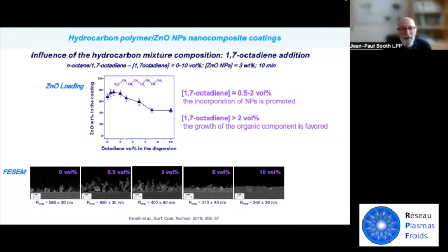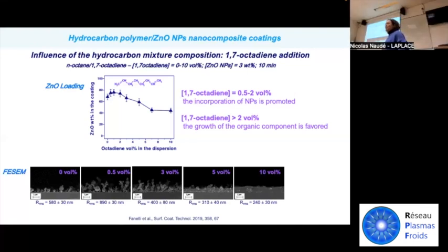Okay. So maybe the durability would be an issue in that environment, I guess. The durability is always an issue, for instance, in the field of catalyst immobilization. There are many things that can be considered, for instance, the composition, the reduction of the thickness of the material during operation, and so on. It's always an issue. But to have a material that can really withstand prolonged operation is really interesting, because even, for instance, in our case, we use in photocatalysis an inorganic TiO2 coating.